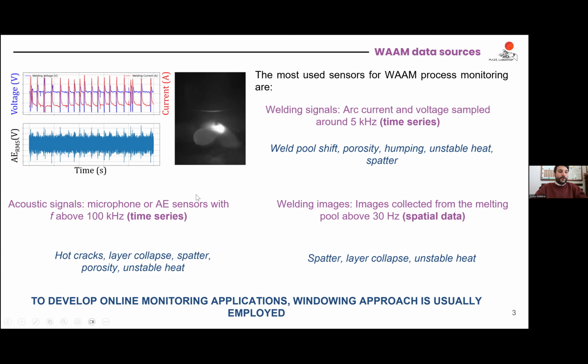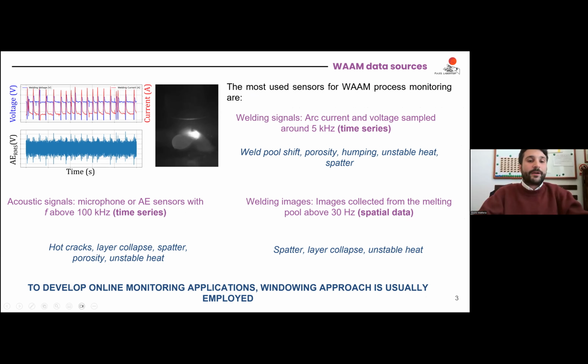You can use, however, also acoustic signals. And for acoustic signals, you can use microphone and acoustic emission sensor that are more like vibration style sensors, let me say, in which you are going to collect data not at 5 kilohertz frequency, but much higher, like 100, 200 or 500 kilohertz. And when you are going up with the sample frequency, you can detect stuff like hot cracks and porosity. And porosity, not only, let me say, big porosity, but also small porosity that happens during the solidification of the metal. But at the low sample frequency, you can also detect layer collapse and unstable heat input during the process.